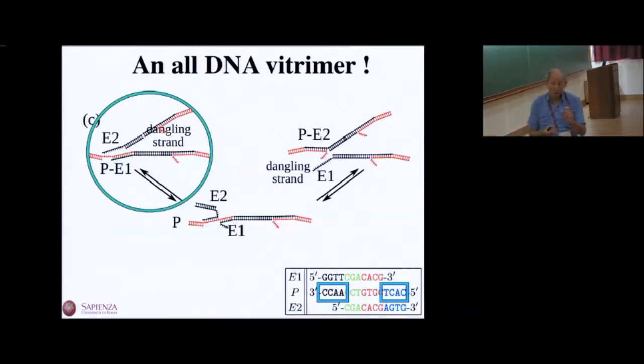Yes, you want first that all 4 or 5 bases stick there, and then swap. Exactly. Well, it's a random walk process. So at the end, you can either evaporate the incoming strand or evaporate the existing strand. If you evaporate the existing strand, then you swap the bonds, because this one is now bonded to that one, and this evaporates away. Maybe with this movie, you can follow it a little better.